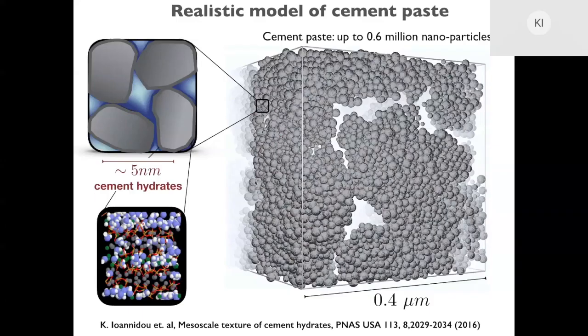Here you see the view of this material from simulations at the smaller scale. The simulation box that you see here is around 0.5 micron. The gray spheres are the calcium silicate hydrate. You see them in the zoom on the side, which are nanograins of a few nanometers, around 5 to 10 nanometers. And these nanograins, if we zoom in inside them, have a very complex atomistic structure that you see on the bottom. At this scale that we are working at here, the mesoscale, we don't keep all the chemistry, otherwise the simulation would be very heavy, but we carry this chemistry through the effective interactions of the calcium silicate hydrates.